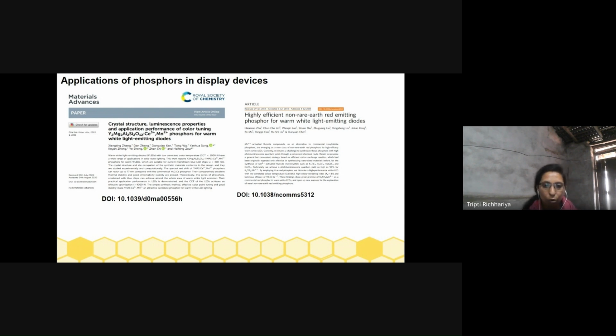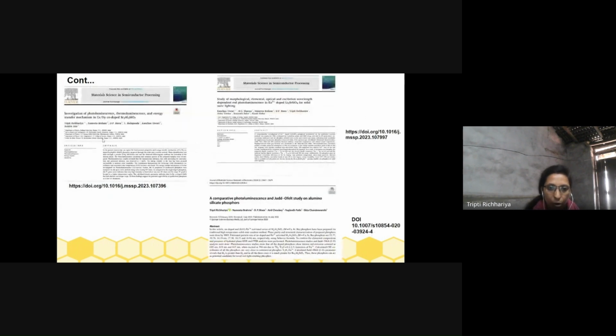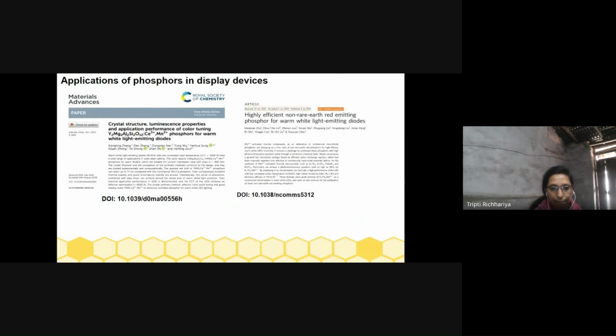So there are several works going on for the fabrication of white light by doing many modifications in the host lattice, or by using different host lattices. For example, in the first literature, the author replaced magnesium and silicon in place of the aluminum in the commercial YAG phosphor, and his findings reveal that the CCT of the phosphor is low, up to 4000 Kelvin, while the correlated color temperature of the commercial phosphor is up to 8000. So the CCT is lowered by modification of the host lattice, as well as by using a different lattice, we are able to increase the efficiency of the LED that is fabricated.